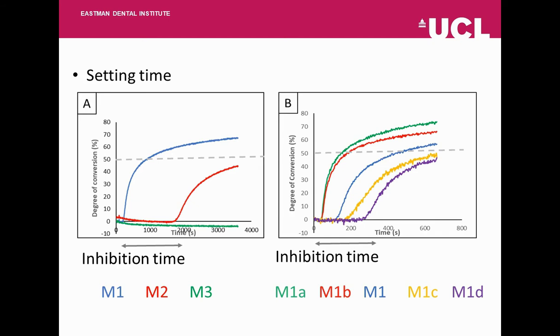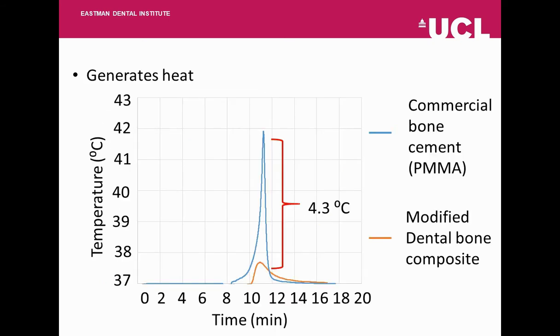Furthermore, during this reaction process, I mentioned heat is generated. So using a differential scanning calorimeter, the heat generated during the polymer conversion was measured to compare between our formulated composite and the commercial PMMA. The difference in heat generation was 4.3 degrees Celsius, and according to literature, temperatures of surrounding bone exposed to PMMA can exceed 70 degrees Celsius.